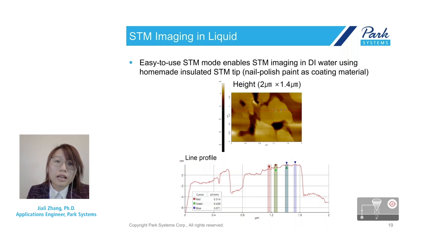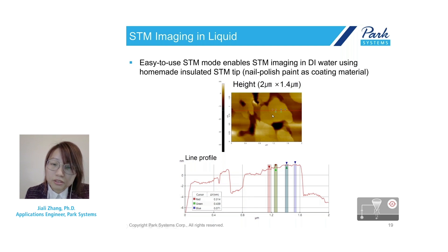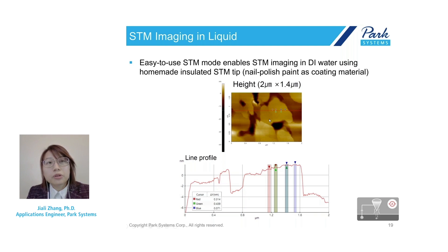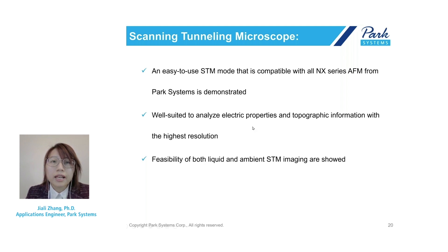Let's look at the results. The imaging was performed using our Smart Scan software. Here is a 2×1.4 µm image area where you can still see multi-layer gold terraces. The terrace looks slightly different from the previous sample imaged in air because this sample was deposited by thermal evaporation — a different preparation method. The line profile still shows ångström-level height differences between different layers of gold. This demonstrates the capability of the Park Systems AFM in performing STM mode in both liquid and air.